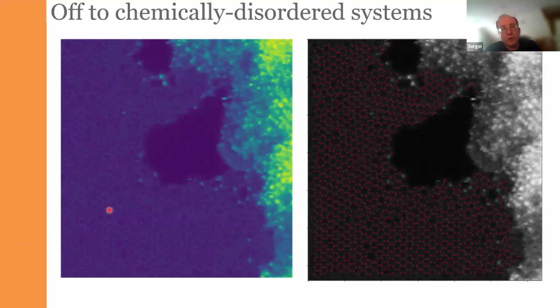So how does it work for more complex cases? Let's look at the example of the system with the chemical disorder. So this is graphene. So you can see carbon atoms. This is the contaminants, which have a lot of silicon atoms. This is the hole in graphene. So you can see the bright dots here. These are the silicon atoms inside the material. This, by the way, is brighter than silicon, so that's probably iron.